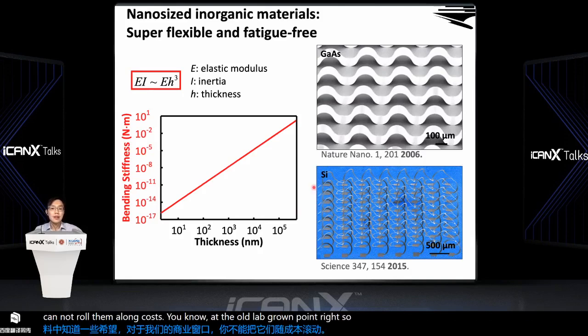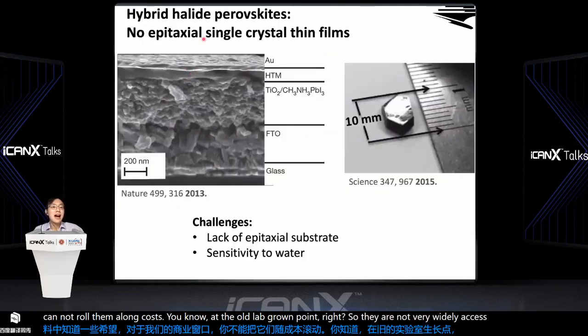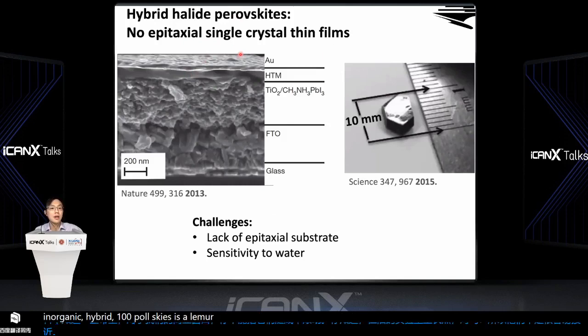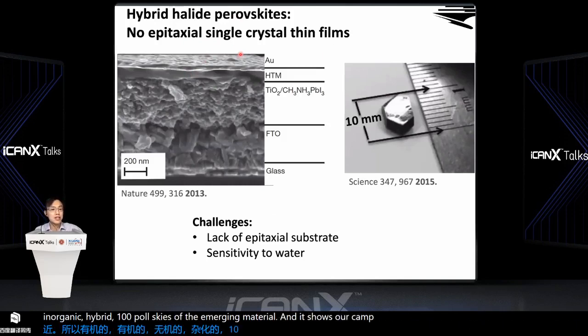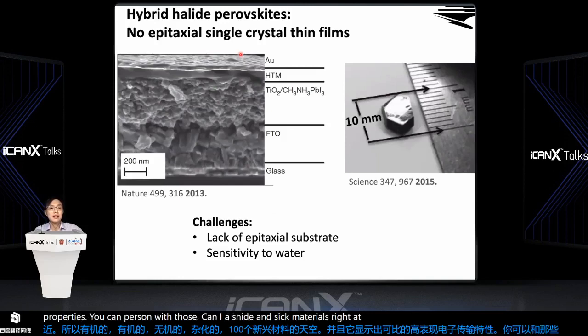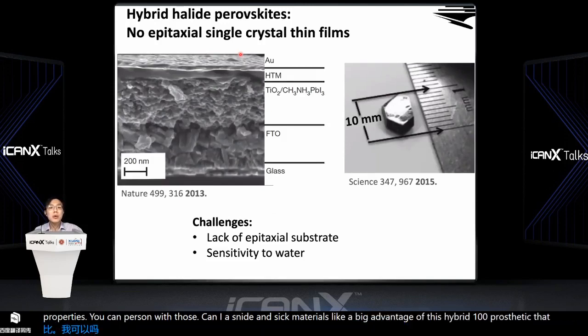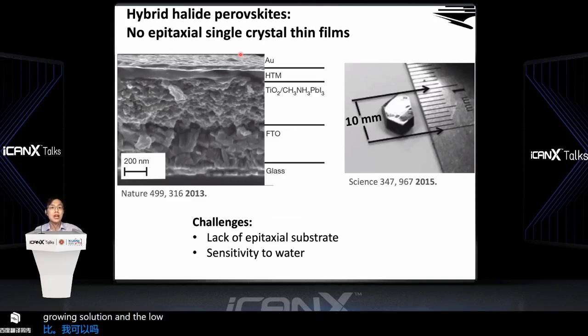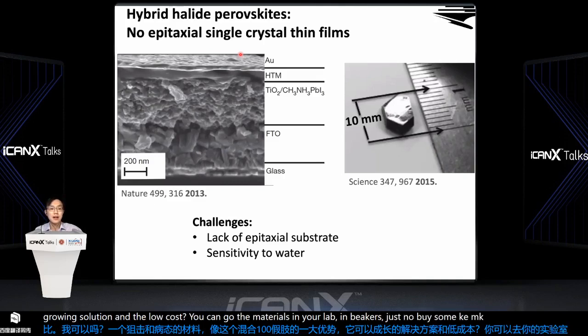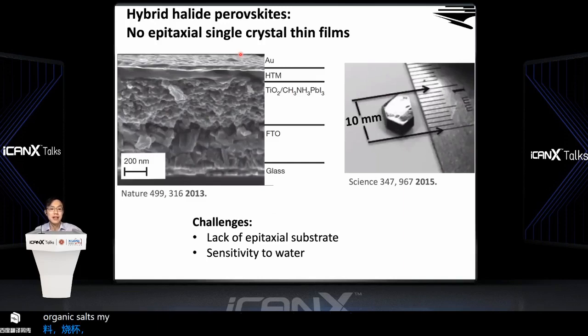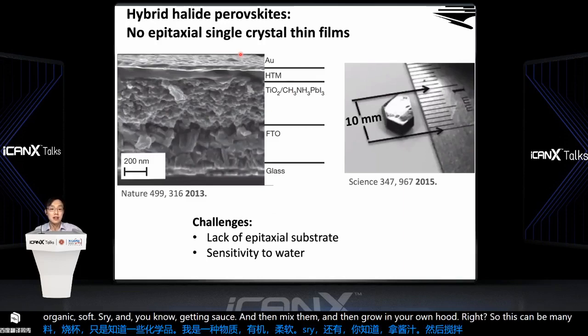So organic-inorganic hybrid halide perovskite is an emerging material, and it shows comparable high-performance electronic, optoelectronic, and transport properties in comparison with those gallium arsenide and silicon materials, right? A big advantage of this hybrid halide perovskite is that it can be grown in solution at a low cost. You can grow those materials in your lab in beakers, just with some chemical substances, organic salts and inorganic salts, and then mix them and grow them in your own hood, right? So this can be manufactured at a large scale.